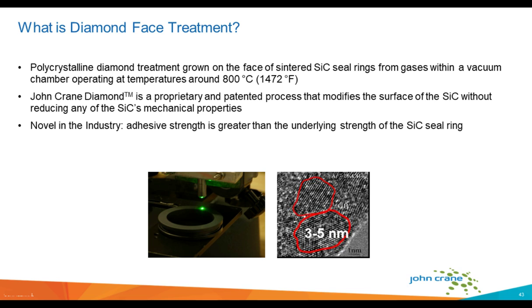It's a really unique technology in terms of this is not a coating or something that's sprayed on a seal face. This is surface engineering, if you will. It's a surface treatment where polycrystalline diamond is grown on a mechanical seal ring. We utilize sintered silicon carbide rings for the majority of applications. There are some other hard face materials that could potentially be used, but the majority is going to be sintered silicon carbide.